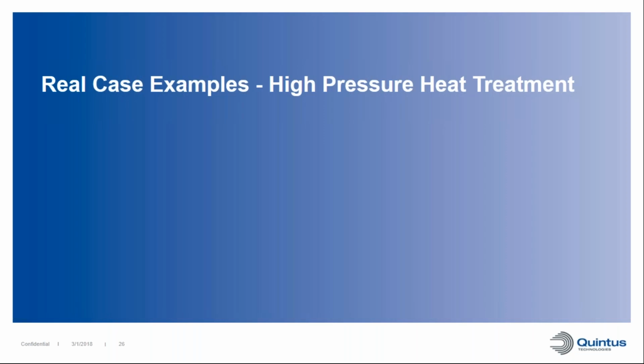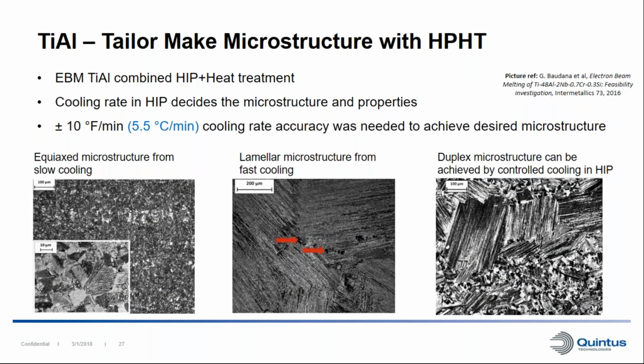So now I want to show you some real case examples of high pressure heat treatment. If we start with titanium aluminide, where we have done some trials with combined hipping and heat treatment. And for this material, the cooling rate, in the end of the heat treatment, very much decides the microstructure and thus the properties of your material. So if we look on the lower part of the slide here, these are from some trials we have made. If you cool slow, you get an equiaxed microstructure. If you cool fast, you get a lamellar microstructure. And if you cool with an intermediate rate, you get a duplex microstructure. And normally for this material, it's a duplex microstructure that you want to achieve to get the best creep properties.